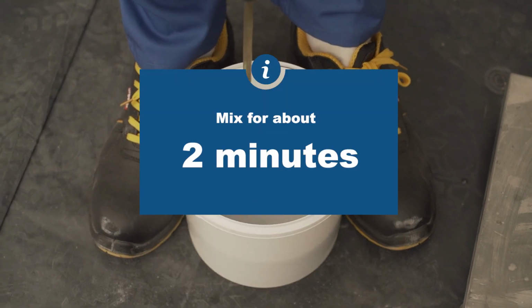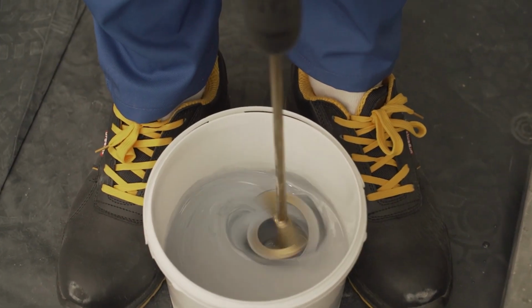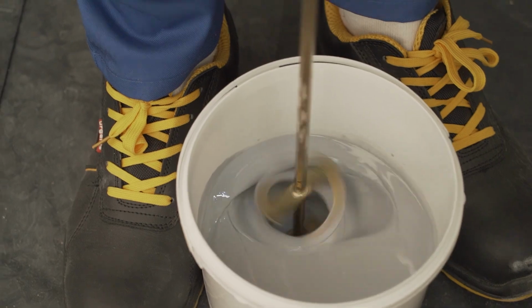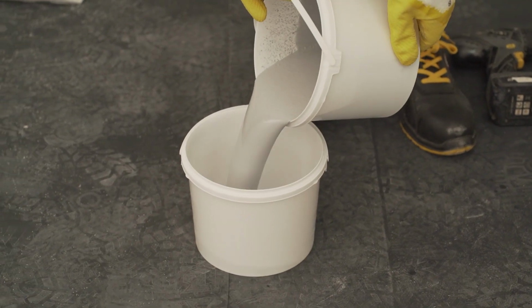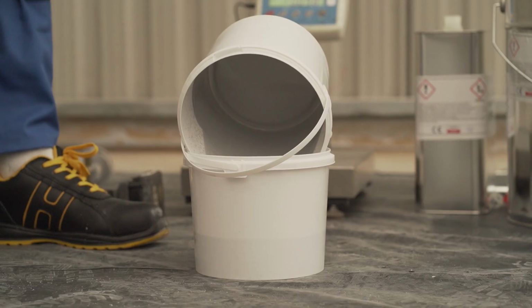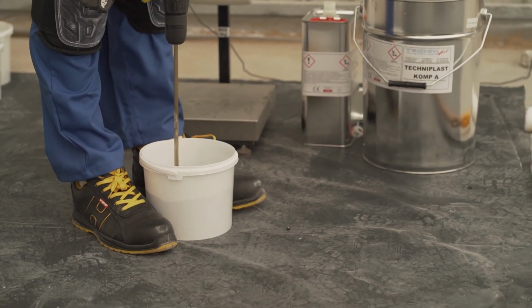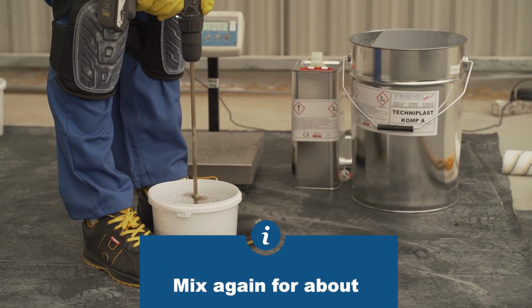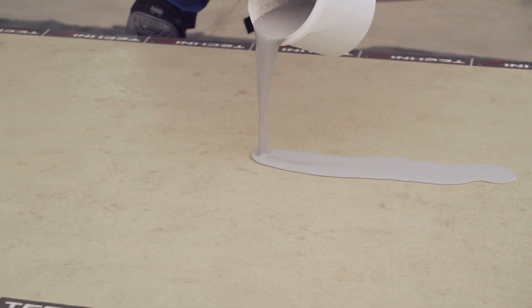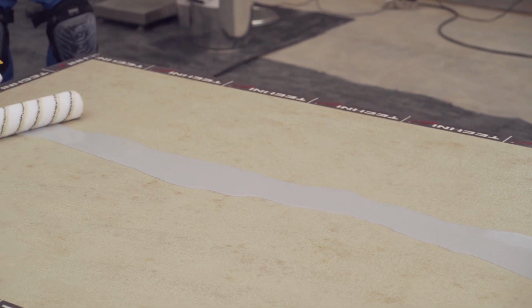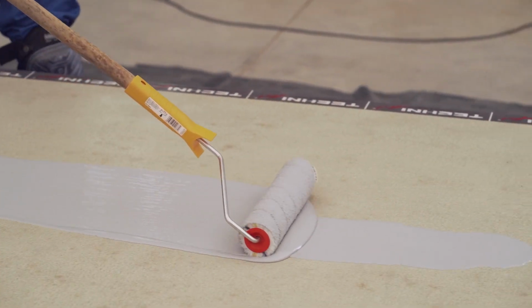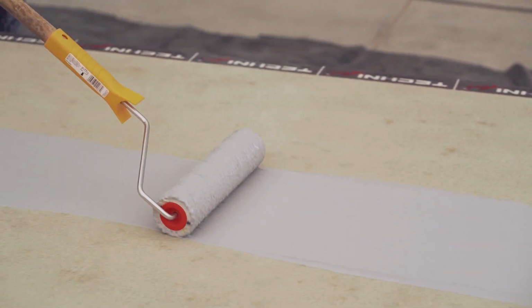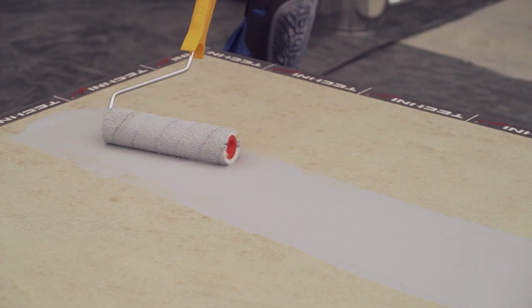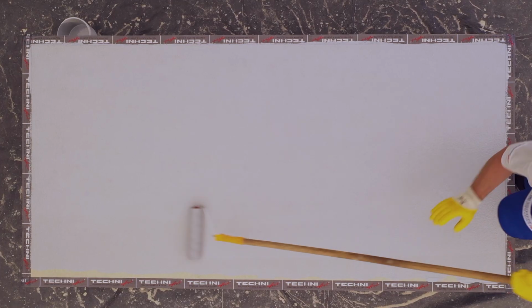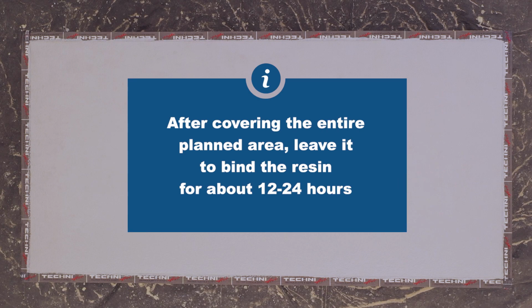Mix with a low-speed mixer, for about 2 minutes. In order to avoid excessive aeration of the material, it is recommended to use a stirrer with a speed of about 300 revolutions per minute. Pour the material into a clean container and mix again, for about 1 minute. Due to the occurring chemical reaction, the material should be applied immediately after mixing. Do not leave mixed material in the package. The Techniplast resin should be evenly spread on the previously planned working area and then rolled with a resin roller using the cross method, which guarantees even distribution of the material. After covering the entire planned area, leave it to bind the resin for about 12 to 24 hours.